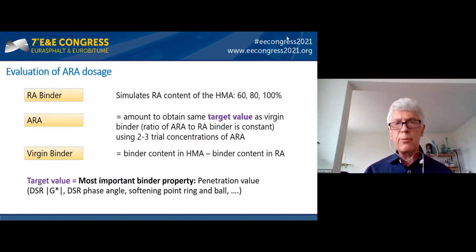So what we actually want to do is to simulate the recycling or the production of hot mix asphalt with 60, 80, and 100% of reclaimed asphalt. So for example, for a 60% rate, you would need 60% of reclaimed asphalt plus 40% of virgin material, which is binder and aggregate. If we break it down to the binder level, this is 60% of reclaimed asphalt binder plus 40% of virgin binder, plus a small amount of ARA just to soften the reclaimed asphalt binder to the same target value as a virgin binder in this case.